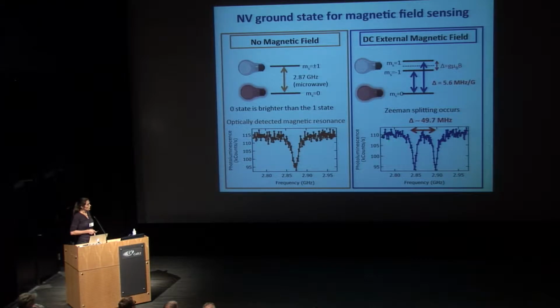An important thing to know is that the sensitivity, our ability to measure very small changes in the magnetic field, is going to depend on the line width of these peaks. And the line width of these peaks is fundamentally limited by quantum decoherence, which is sometimes called T2 star in the NMR community. That's one of the reasons why the NV center is a good sensor: it has very narrow lines.